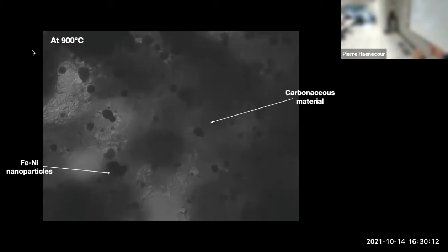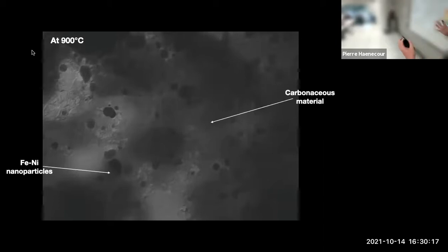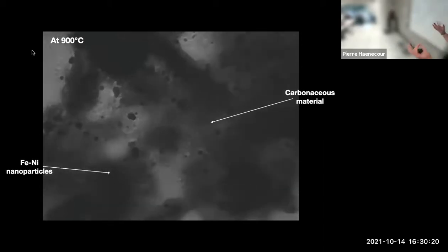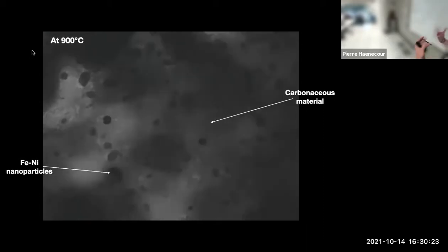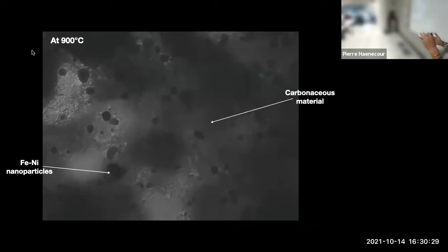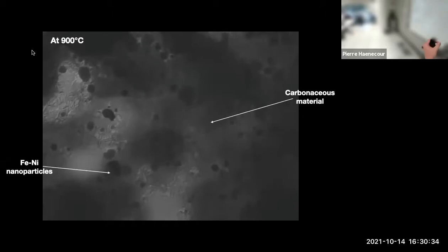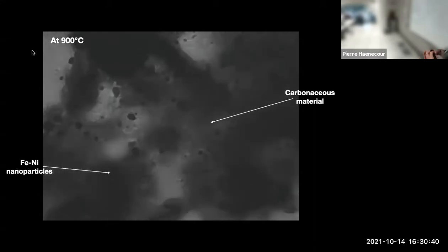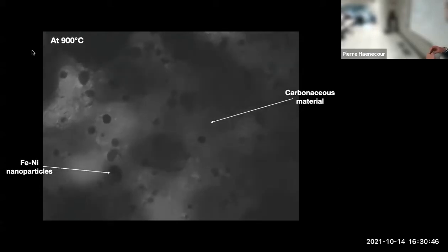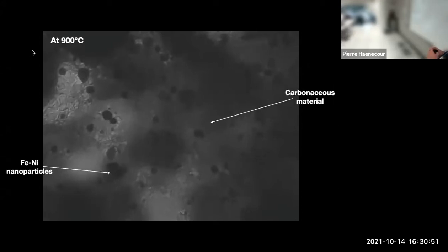You can see what's happening to the sample: it's actually melted particles swimming around in the carbonaceous matter, agglomerating together to form larger particles. You're literally accumulating them, forming larger and larger iron nickel particles. Interestingly, because the movie started just as we were reaching 900 degrees, it shows how the focus changed as you heat the sample. It's out of focus at first until we actually reach 900 degrees. You can see it's happening everywhere. It's just swimming around everywhere.